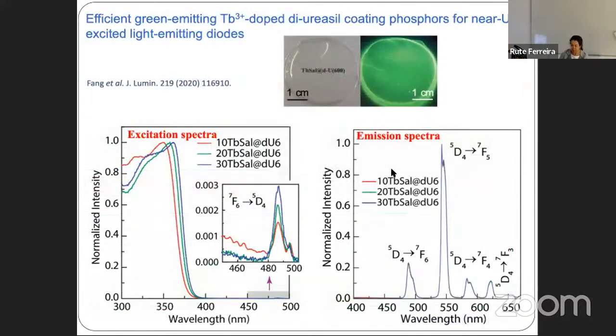So the hybrids are typically processed as freestanding films. Here you can clearly see that the final films are transparent, and under UV radiation, you can see the bright green color. And why do we have those properties? Here I have the excitation spectrum that nearly overlaps the absorption one. So we can clearly see that these materials essentially absorb the ultraviolet, meaning that they can potentially be excited with a UV LED, and then the emission and the excitation in the ultraviolet display the very well-known 7F_J transitions of the terbium.